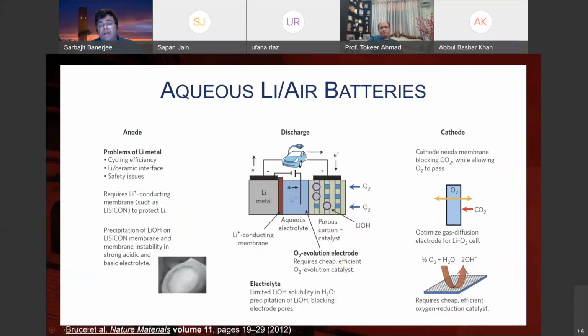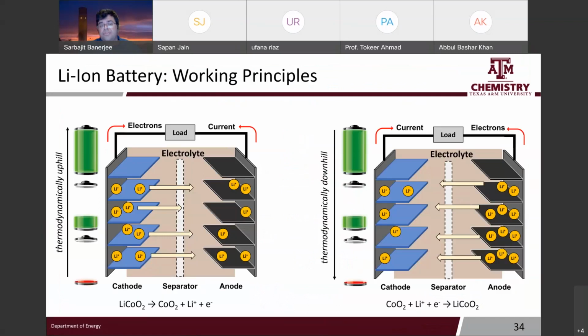And then again, you have to optimize the gas diffusion electrode so that you can separate out carbon dioxide, and then need a membrane to block CO2 while allowing oxygen to pass, and then a cheap, efficient catalyst that can mediate essentially this reaction, the oxide to hydroxide formation. This is a big challenge, and because these challenges remain to be resolved, again, it's a fantastic concept, but it hasn't really come to full fruition to the extent that you need for commercial applications, right? And of course, we don't want to have the lithium metal get passivated, so we need a lithium conductive membrane that will protect the lithium and make sure that you don't have lithium hydroxide form on the surface of the anode.